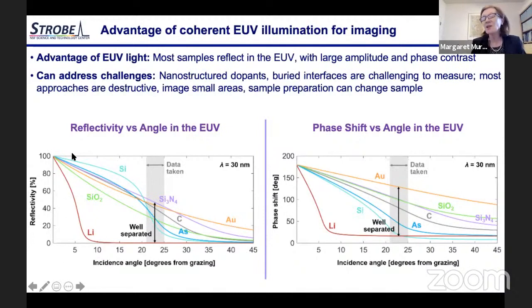And just like with visible light, everything is reflective at glancing incidence, and that's the same for EUV light. But the other wonderful thing is that there's a nice contrast. And since coherent imaging gives you the amplitude and phase of your reflected light, there's even a bigger contrast if we extract the phase. And so what that allows us to do is make a microscope where we can put a nanostructure in there, and we can build a model.